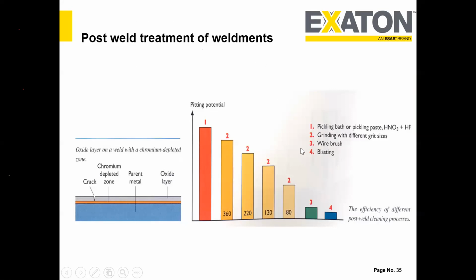Several times I got a question: we followed everything, all the welding was good and looks nice, but if we keep it in our workshop or outside, within 1 month or even 15 days, we can find a brown color on the ripple. Why did it happen? It is basically a potential area of corrosion. Although you take care of the right filler metal and right parameters, if you don't do this post weld cleaning or post weld treatment, when you do the welding you are destroying the chromium oxide layers with a lot of undesired things. So we should make sure that we remove all the undesired oxide formation layers with proper cleaning.